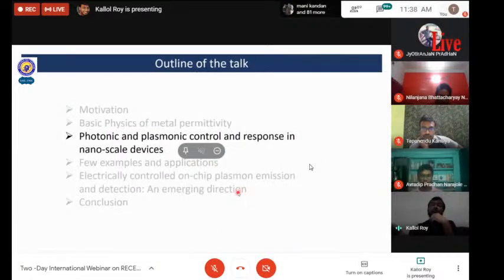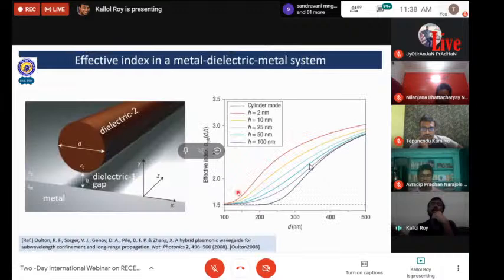So let's look now at a few examples of control via specific device design in the nanoscale. This is one of the famous metal dielectric systems, which shows that the effective index can be controlled. For example, you see a dielectric rod with a dimension of d, placed on top of metal with a small gap of certain height, which is filled by another dielectric. The effective index of this system, which you can also relate to the permittivity, changes as you change the gap. Say, for example, here the gap is tuned from 2 nanometers to 100 nanometers, and hence the effective index changes drastically.